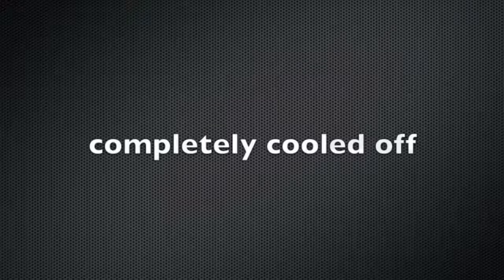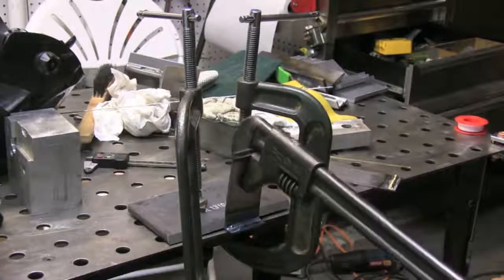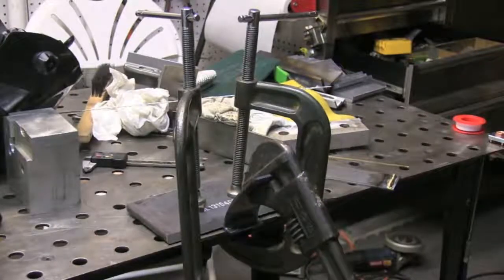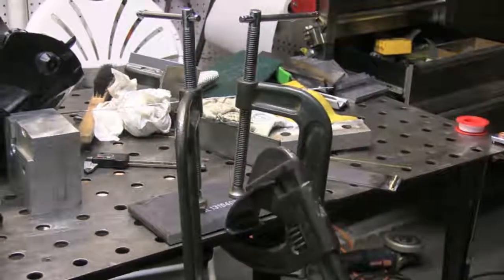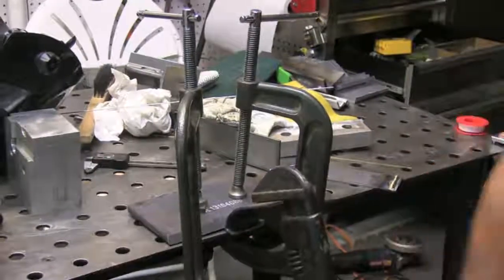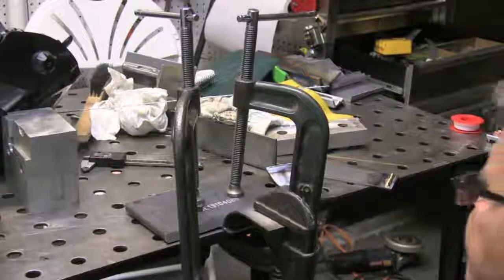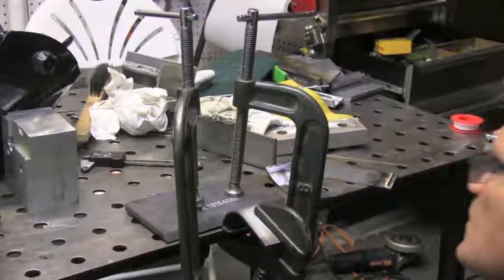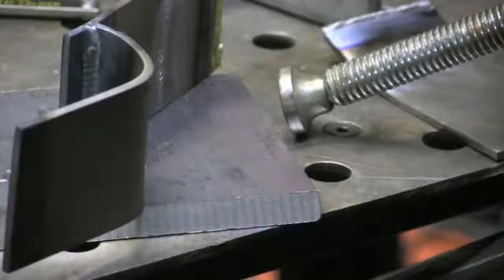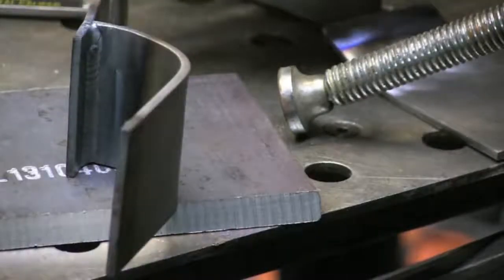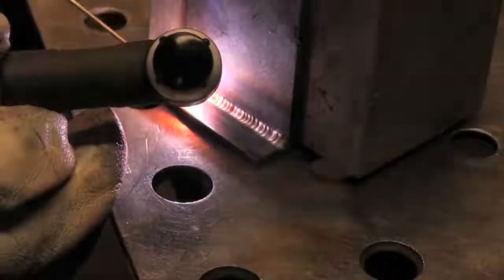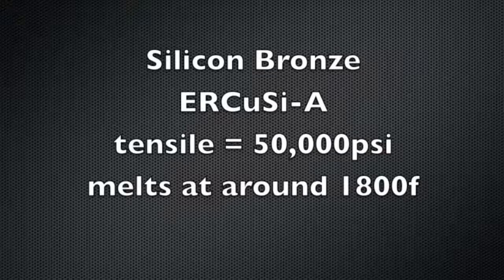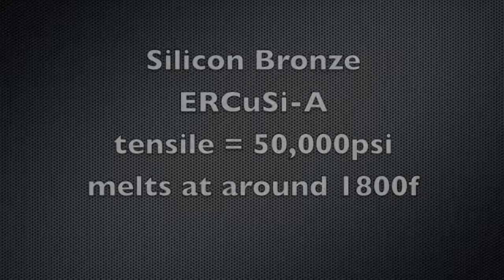All right, let's cool that off and then put a Ford wrench on it and clamp it down to the table and see if we can break it. And even though that's 1/8 inch cold rolled steel with only a 1/8 inch leg size fillet, which doesn't wind up being a full 1/8 of an inch of metal, it's still held up. If I'd have made a smaller fillet, probably wouldn't have. But again, watching that metal go all the way down into the corner, I'm getting penetration into the root of the joint.